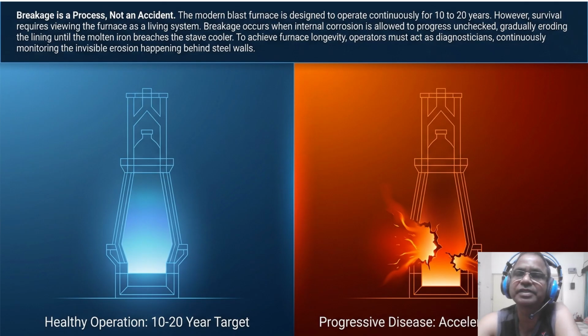So what? Here is the simple answer. If you are not monitoring the invisible erosion happening behind those walls, you are effectively flying blind. Once that internal disease progresses unchecked, the structural integrity of your primary asset is already compromised beyond simple repair. We must treat every thermal shift as a symptom of this progressive erosion. This disease doesn't attack randomly, it follows a very specific pathological pattern in the lower hearth.